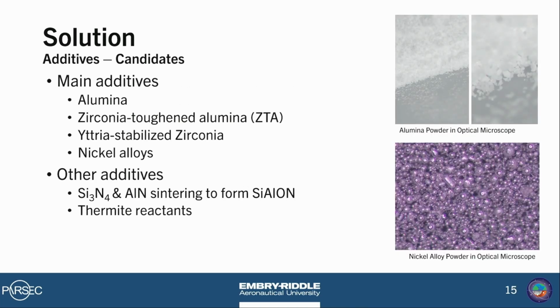So far, we have 4 main candidate additives that we are researching, and they are all common thermal spraying feedstocks. 3 of them are ceramics, and they include alumina or aluminum oxide, zirconia toughened alumina or ZTA, which is essentially just alumina with around 5 to 20% zirconia added by mass, and then yttria stabilized zirconia. We also have one main metal additive that we're considering, and that's nickel, which we have just recently begun researching after a series of successful conglomeration experiments were conducted with a particular nickel alloy that Grant here will be talking